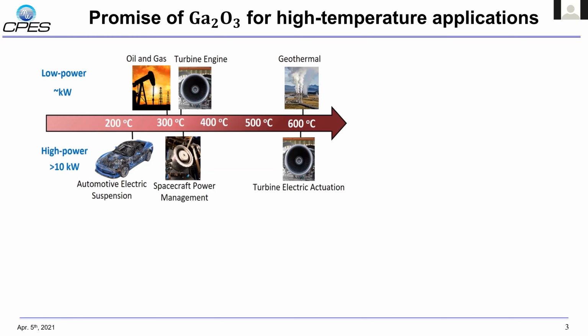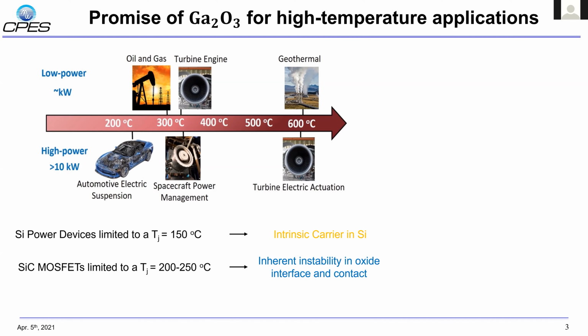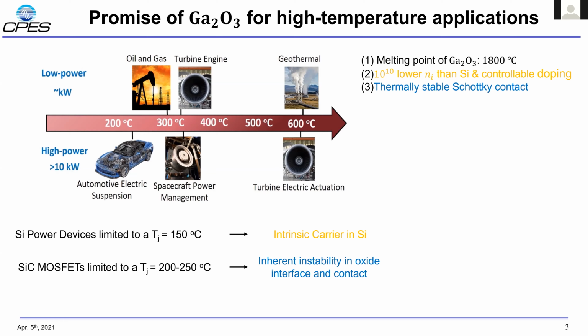Now let's talk about the promise of gallium oxide for high-temperature applications. As we all know, as the operating temperature for power systems goes higher and higher, there will be many problems. Silicon power devices are limited to a junction temperature of 150 degrees C because of the high intrinsic carrier concentration in silicon. Silicon carbide MOSFETs are limited to a junction temperature of 250 degrees C because of the inherent instability in oxide interface and contact. However, gallium oxide has an ultra-high melting point, and it has much lower intrinsic carrier concentration because of the wide bandgap, which means that controllable doping at higher temperature can be achieved. And thirdly, thermally stable Schottky contact has already been developed.